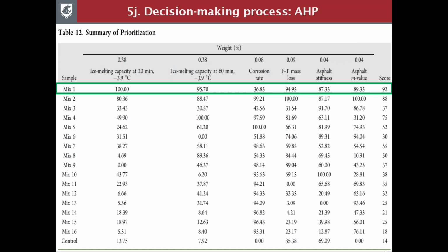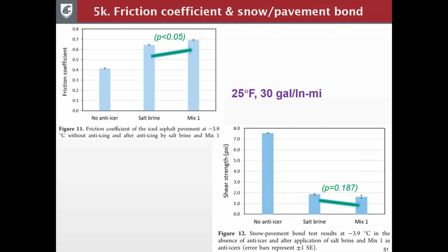We look at control, which is ranked 14 out of 100. So we further study the performance of this mixed one versus the salt brine control. For anti-icing at 25 degrees Fahrenheit, 30 gallons per lane mile in the lab, we demonstrate the friction coefficient is significantly better with the mix 1 anti-icer. So p-value less than 0.05.